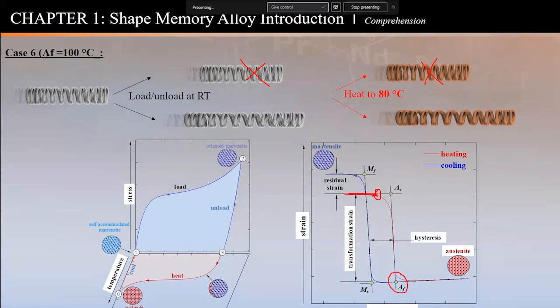So in order for you to get it to transform, to remember the shape, you have to heat it past this transformation. So you have to change the shape. This is the dimensional change. So you have to go past this critical temperature known as the AF. So the path that we have here: you deform it at room temperature, you create a stretched length, and then you heat it to 80 degrees. Actually, nothing happens. It stays like this. If I heat it to 180 degrees C, past the AF, then yes, it will shrink and go back.